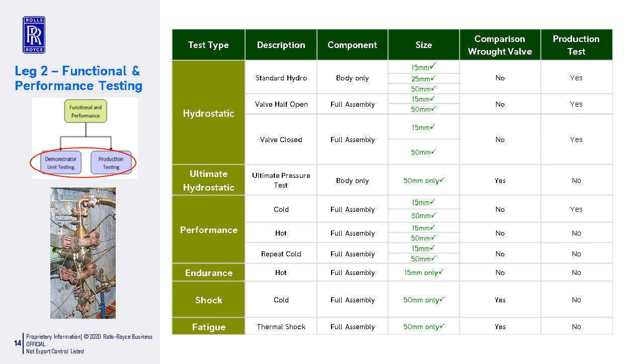So, as well as the extant testing methods that are applied to the current components as part of production, such as component hydro tests, valve seat checks, hot and cold valve testing, we also specified tests that go beyond the code requirements, if you like. So we also undertook an ultimate hydrostatic pressure test, an endurance seat performance test, looking at wear of the seat, a shock test, and also a thermal fatigue test. So the next few slides just expand on these tests.